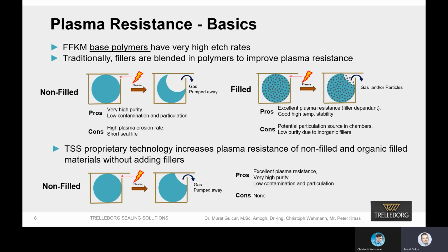The filler particles will shield the base polymer from plasma exposure up to a point, and the elastomers finally have better plasma resistance. So when we talk about an example here, a non-filled material, which means that there's only the base polymer and the curative, the most basic rubber compound or elastomer material we can get. So if you have such a material, as you can see, if you say that this seal is in the groove, obviously in some applications these seals are exposed to plasma, and from the process side, from the right hand side, if the plasma strikes the material, obviously over time the non-filled material will be etched away as any other organic material.